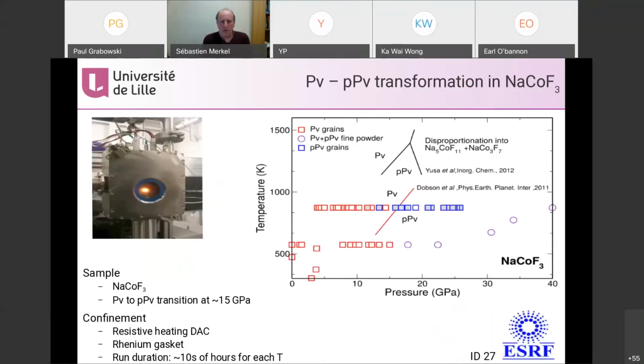So I'm going to show some illustrations going from a perovskite to a post-perovskite phase. I'm not going to look at the true phase in the deep mantle because it's at the moment outside our reach for this type of experiment. Here we worked on this cobalt analog because of the pressures and temperatures you can reach with a resistively heated diamond anvil cell. What we did is we heated a sample to 900 Kelvin, compressed it into the perovskite field, converted it to post-perovskite, and then we looked at the grains in perovskite before transformation, then the grains in post-perovskite after transformation. And then we are going to go back from post-perovskite to perovskite.